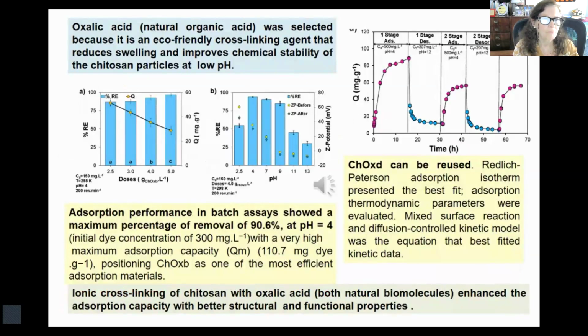Oxalic acid was selected because it is a natural organic acid, an eco-friendly cross-linking agent that reduces swelling and improves chemical stability of the chitosan particles at low pH. Adsorption performance in batch mode shows a maximum percentage of removal of 90% at pH 4. Ionic cross-linking of chitosan with oxalic acid enhances the adsorption capacity with better structural and functional properties.